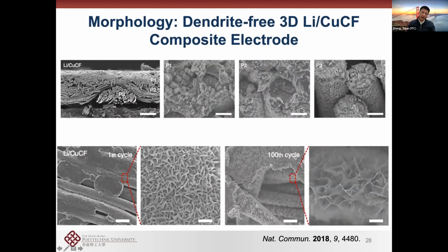And then you can have this anode look like this. This is a cross-sectional structure of how the lithium metal is deposited on the copper-coated carbon fabrics. The key thing here is that every single fiber was coated with a very nice layer of lithium metal. When you cycle the cell, as an electrode, and electrochemically charge and discharge it, you see that at the very beginning there are lots of micro patches, which is not good at all. But once you cycle, it's getting better and better, more uniform. This micro patch structure will disappear.